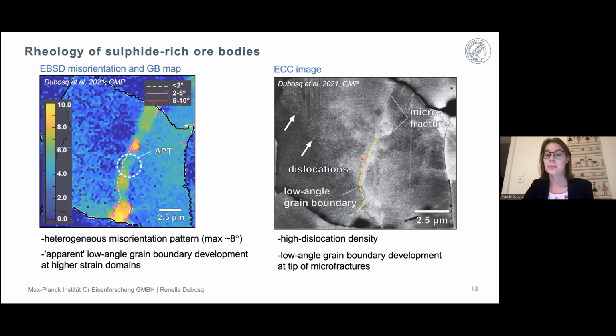And on top of all of this, we notice that there's a clearly high dislocation density in this higher strained region, as well as further away from the crystal. And so based on these images and these EBSD maps, I selected a region of interest in the center of this high strain region for further analysis with APT.